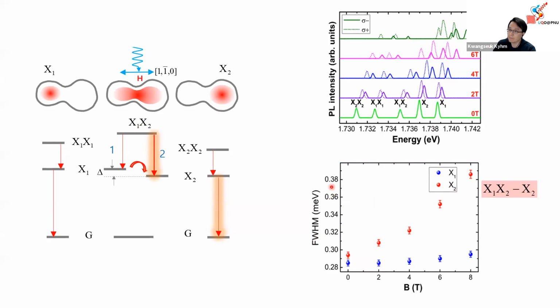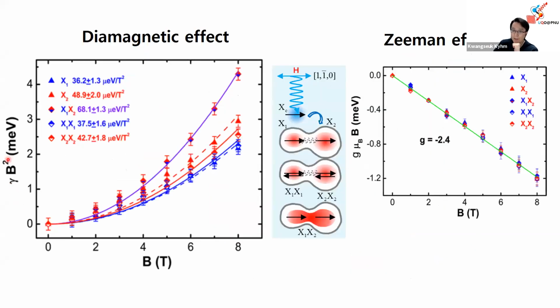We also analyzed the quadratic dependence of the diamagnetic effect. So the coefficient, that one is a diamagnetic coefficient, which is proportional to the wave function extent. So free exciton and local biexcitons are similar, but the coupled biexciton has a large wave function extent. So the coefficient is large. Here it is roughly 68. Others are 36 and 40. Yeah, so it is large. The wave function area is large. On the other hand, g factors are nearly the same for all those peaks.